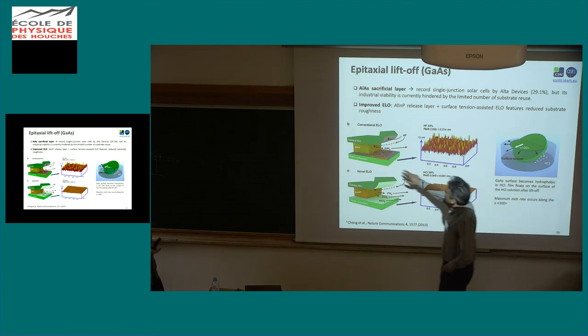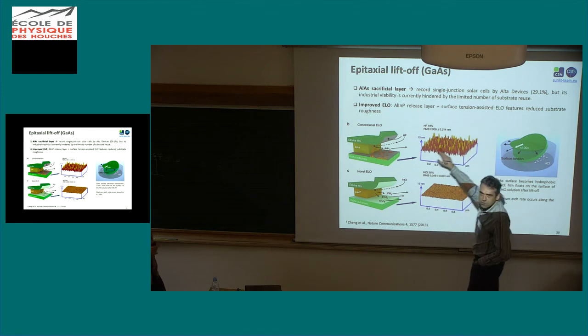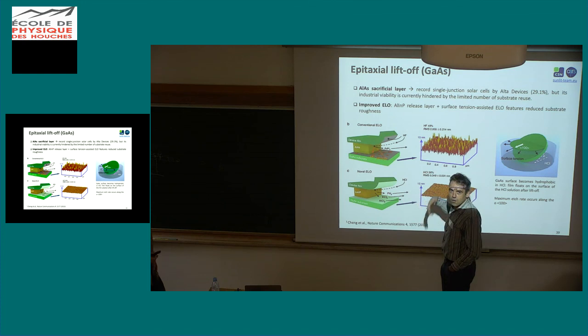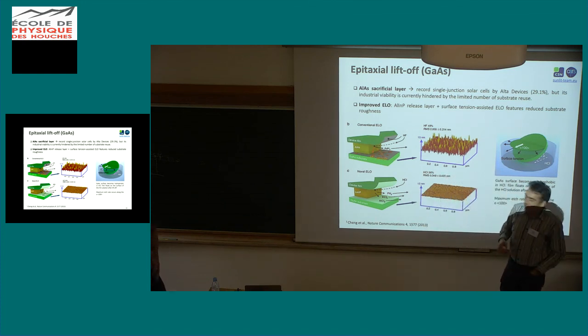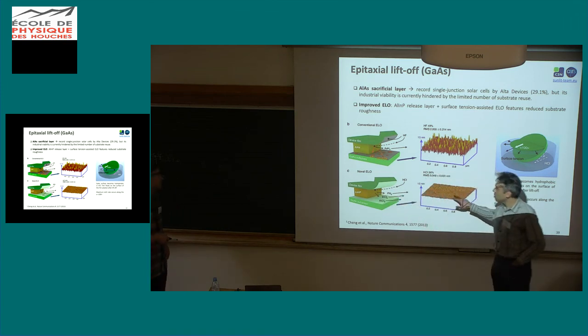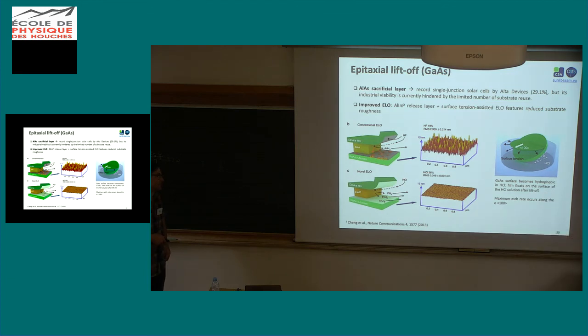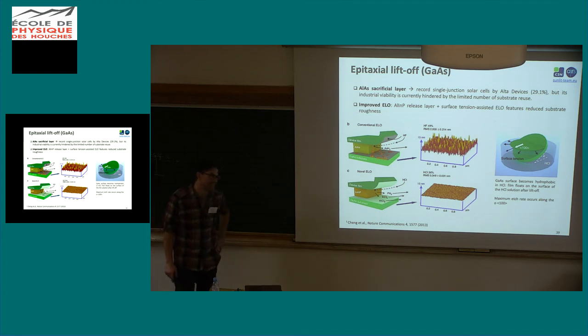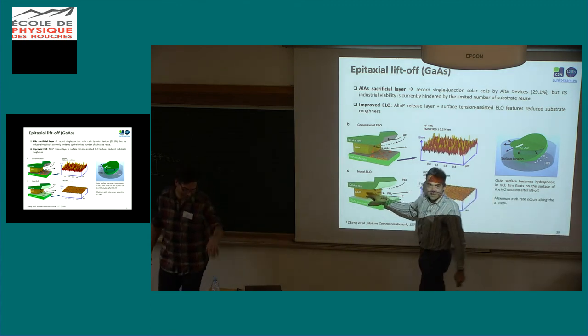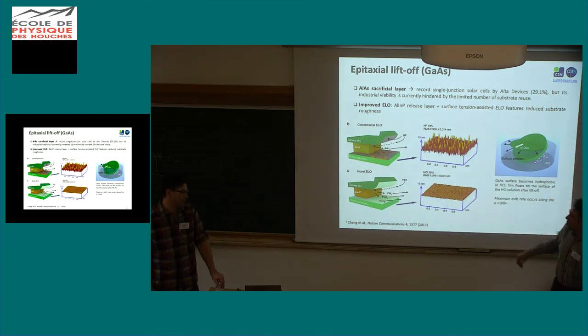So the point here was, if you use this material and you etch it, you have a quite rough surface. So it's not excellent if you want to grow high quality material. You have to go through polishing. And so this material seems to be much better, but actually the best gallium arsenide solar cells are made with AlInP window layer and back surface field. Remember that the nice thing with epitaxy is that you can grow lattice matched materials and ternary alloys, and you can make the heterostructure in one step. And the best window layer to have a selective contact and a passive contact is this material. So the best solar cells use this material for the window layer. If you use it for this liftoff, you will etch it. No, you can always protect it. There's always a workaround. It's not a big deal.